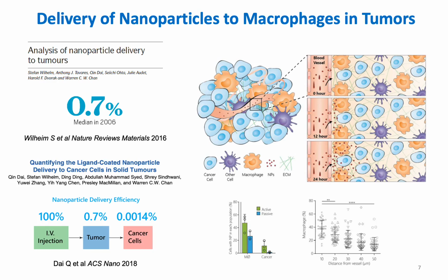These results are controversial, and many other research groups in the last years have reported specific types of nanoparticles improving this delivery. However, what is commonly accepted in the community is that macrophages are more efficient than cancer cells at taking up the nanoparticles. When the nanoparticles reach the tumors, in the tumor vessels, the nanoparticles extravasate and most of them accumulate in the macrophages in the vicinity of the tumor vessels. In this study, they show this accumulation in macrophages for nanoparticles for both active and passive targeting.